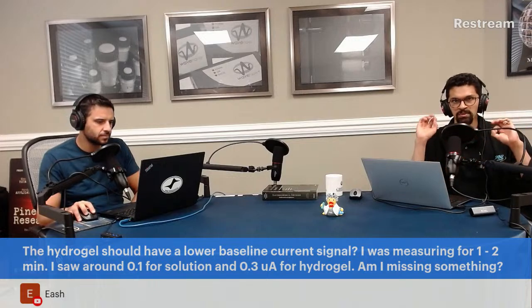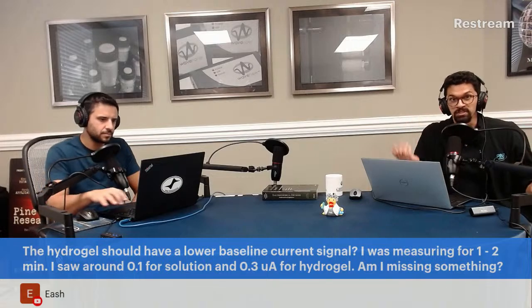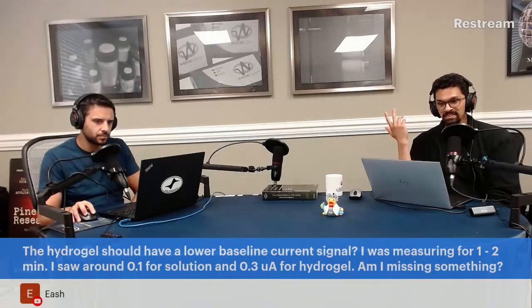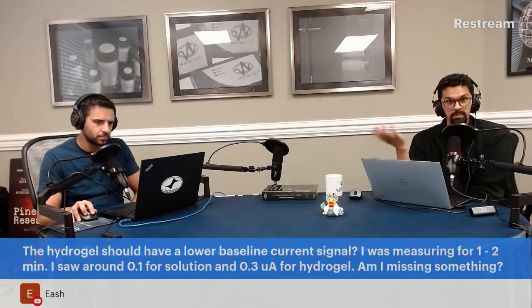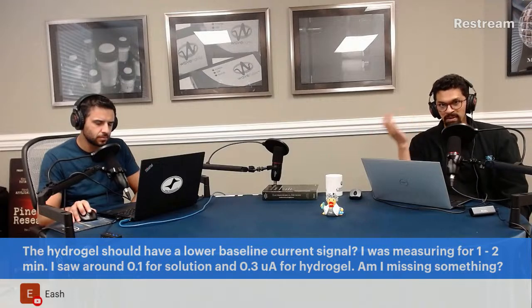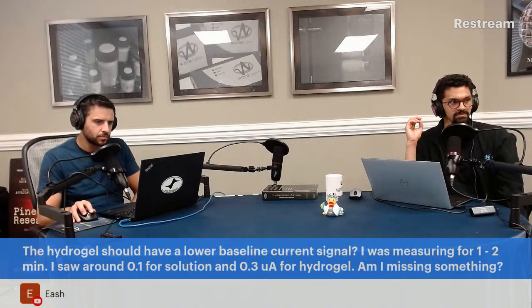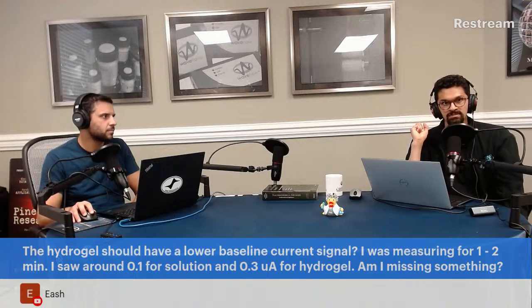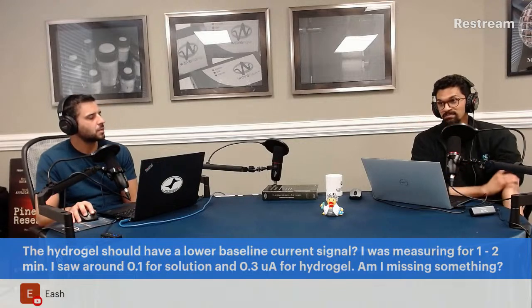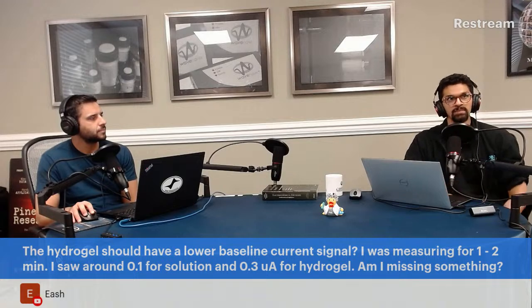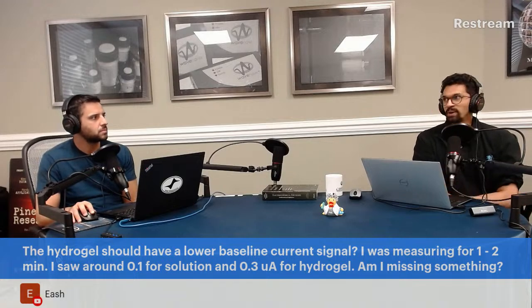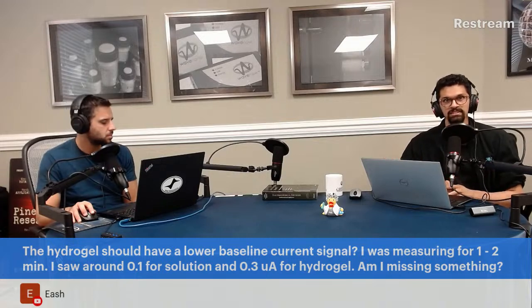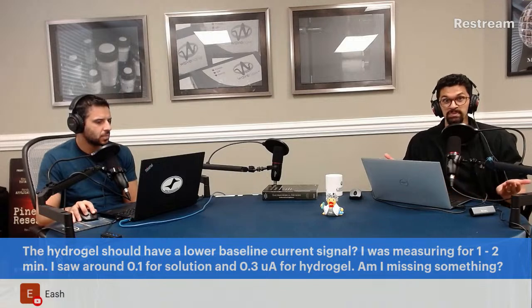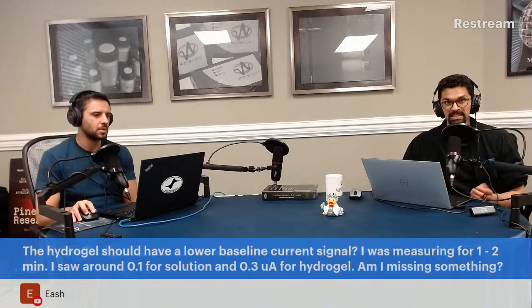Certain things that are important in chronoamperometry: the initial spike in a chronoamperogram is partially double layer charging, but that's just going to be based on the time constant, 5 RC, 5 times the solution resistance and the double layer capacitance. So 1 ohm times 1 farad is 1 second. But in traditional systems, when you have microfarads or even 100 ohms of solution resistance, you're still able to charge this thing on the micro to millisecond time scale.